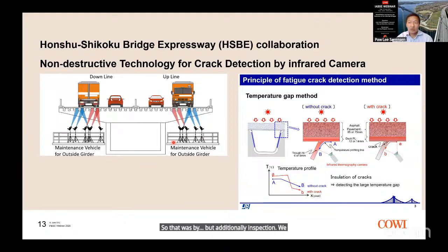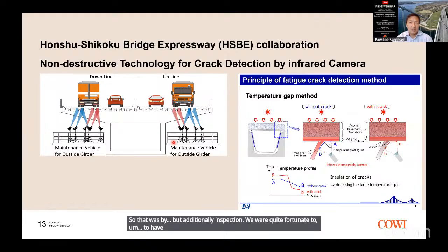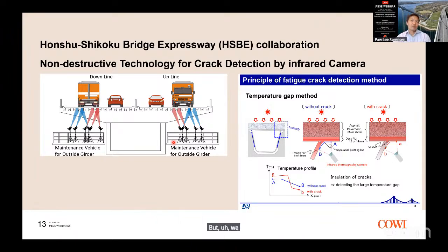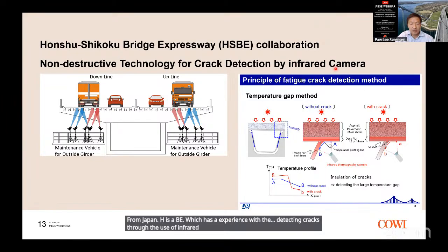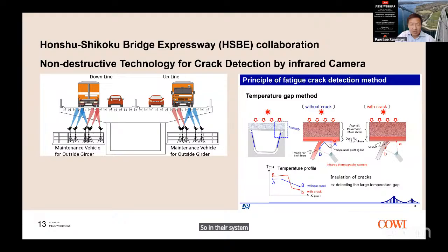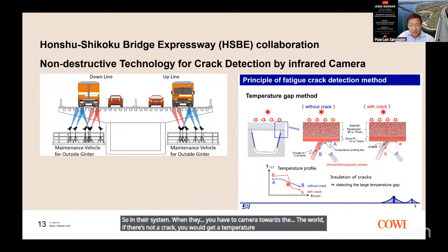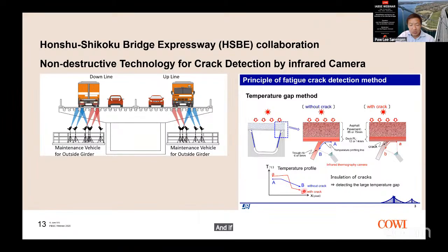We were quite fortunate to have this combination of paints that allowed us to see relatively clearly if there's a crack in the paint. But we also investigated if there are alternative ways of identifying the cracks. And we entered a collaboration with the Honshu Shikoku Bridge Expressway from Japan, HSBE, which has experience with detecting cracks through the use of infrared camera. So in their system, when you have the camera towards the weld, if there's not a crack, you would get a temperature profile similar to the blue one here. And if there's a crack, it will change to a temperature profile similar to the red line here.